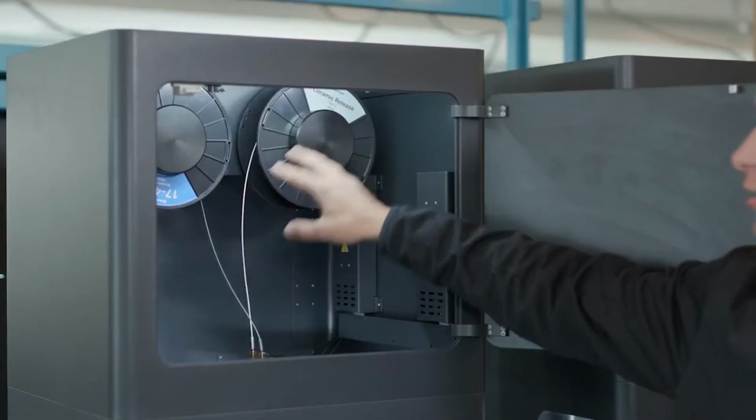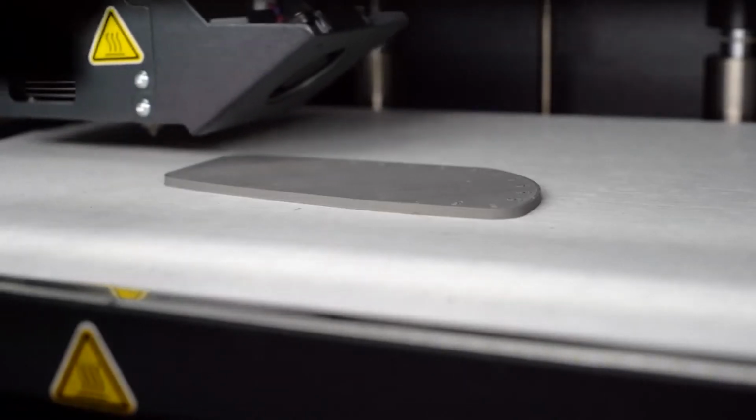So if you're thinking of just metal, absolutely not. You're never going to get an FDM machine hot enough to do that. But with this idea of creating a composite wire that either has a metal wire on the inside with polymer on the outside, or I've also seen where they infuse a polymer wire with metal powder, and then essentially you FDM your part, and then you sinter it and vaporize off all the polymer. Again, going back to this idea of post-processing, now we're introducing more steps because we have sintering and vaporization of the polymer. So yes, it's possible.